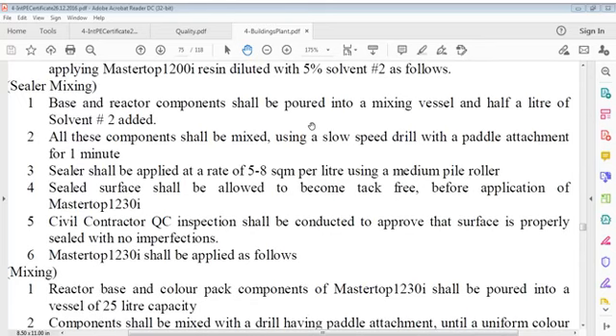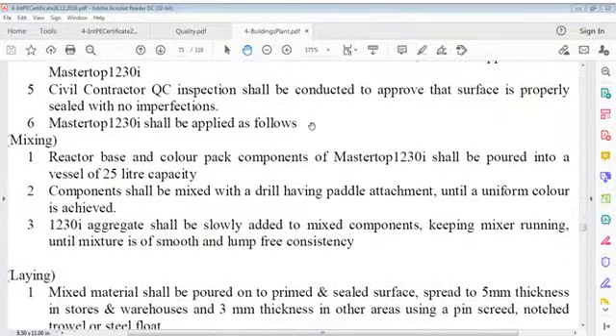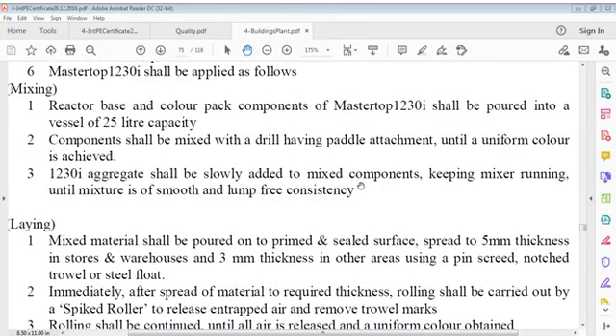Sealed surface shall be allowed to become tack free before application of material. Civil inspection to be conducted. And material shall be applied as follows. Now this was seal coat, now it's mixing of material. Reactor base and color pack components of material shall be poured into a vessel of 25 liter capacity. Components shall be mixed with a drill having paddle attachment until a uniform color is achieved.